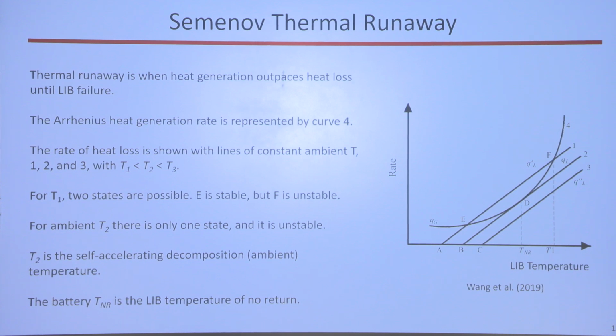Right now, it's nice and stable. But there is another solution here. If we heat this battery up and it goes to point F in quasi-steady state, now this is unstable. If briefly it increases a little bit to the right and the temperature of the battery increases, now the heat loss to the surroundings can't increase at the same rate and it will go into thermal runaway.